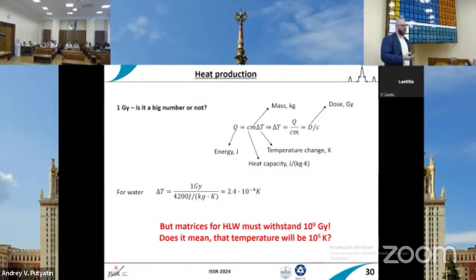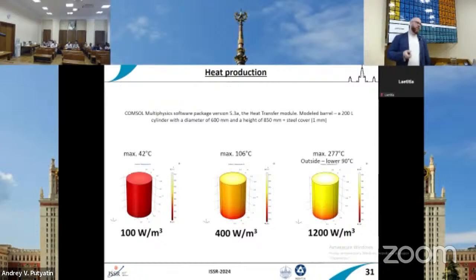But actually, when we are speaking about high-level waste storage, this dose is accumulated during the storage of the radioactive waste. It's not in 1 second. It's in something like 1,000 years. And for this, it is important that our material has a good thermal conductivity, as I mentioned on Tuesday in the previous lecture. Here is one example, a simulation of the cement matrix. If we put in radioactive waste with different heat production rates, you can see that even for very high heat production, 1 kilowatt per cubic meter, it's really high heat production.